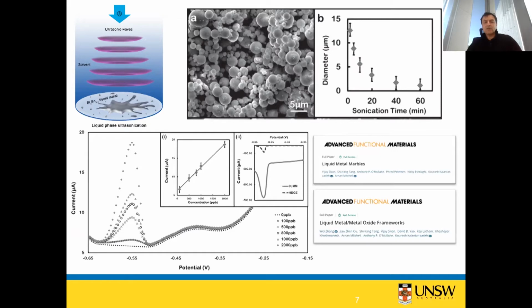But here, the two-dimensional oxide, which is formed on the surface, when you sonicate gallium or EGaIn, alloy of gallium, under a mechanical force, this two-dimensional oxide goes around it and basically makes them stable. So they don't merge together anymore. If you continue sonication, the size of these droplets becomes smaller, smaller, smaller. So like any other nano-sized material, you can start making fascinating things from it. For instance, you can make films of very high surface to volume ratio. These films can be used for many different applications. I just presented one of them here for sensing.